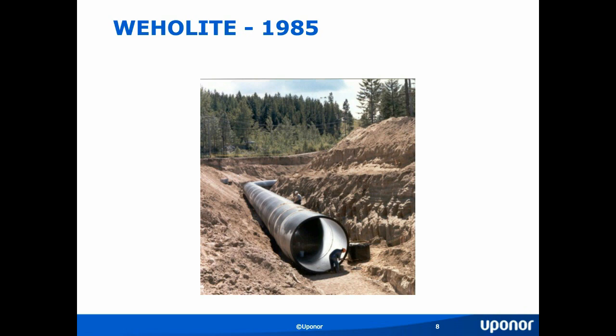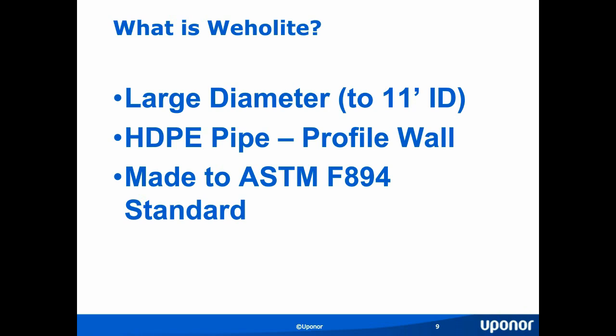Weholite Pipe has actually been around a very long time, around 33 years, and we began production of it in 1985. So what exactly is Weholite Pipe? It's a large diameter pipe ranging anywhere from 18 inches up to 11 feet on the ID. It's made from exactly the same material as our solid wall polyethylene pipe, except rather than extruding a solid circular pipe, we're extruding a profile, say for example 3 inches high by 5 inches wide, and we take that profile and we wrap that around a drum and we begin to weld the inside and outside of the profile together to construct the pipe. And so as you can envision, this would be a helically wound pipe. It's made to a very particular standard, and that would be the ASTM F894 standard.